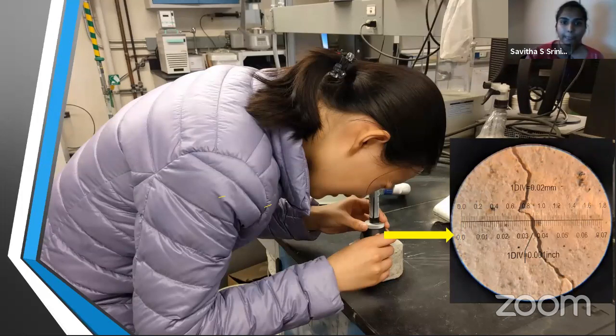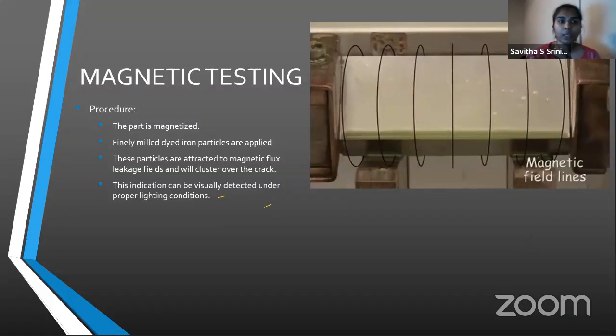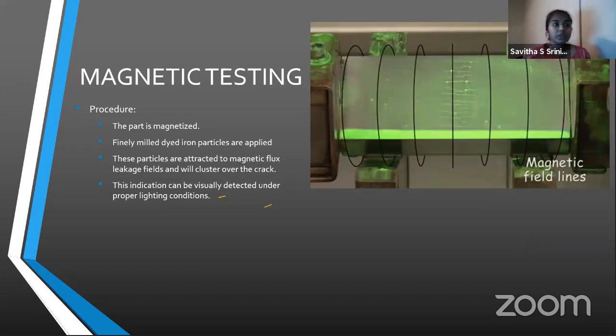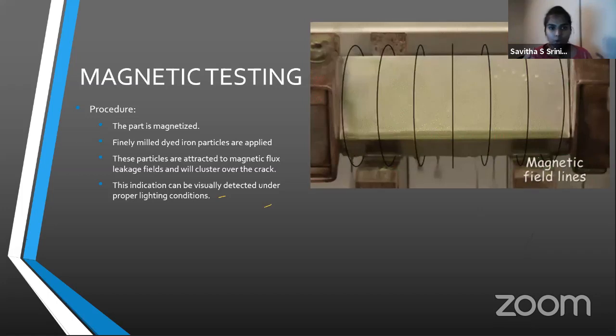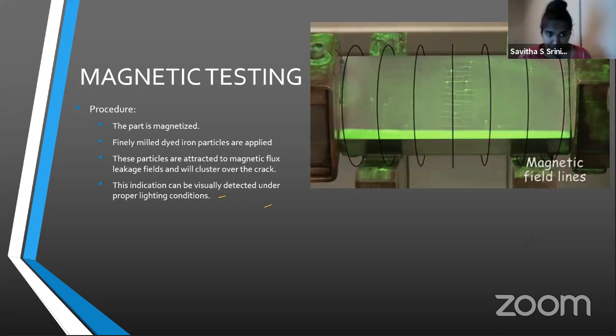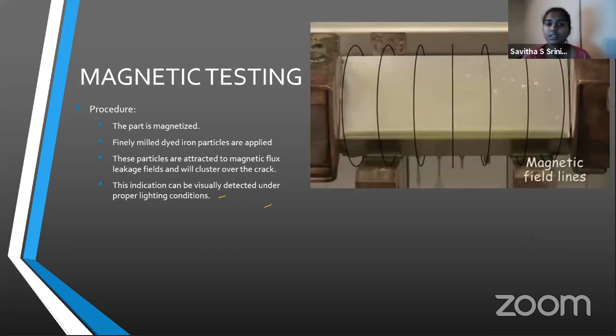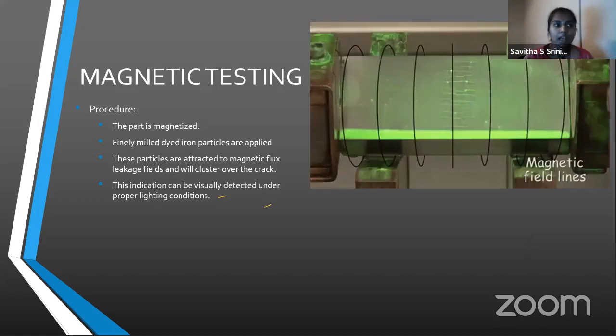The next one we're talking about is magnetic testing. So this one, the procedure is really simple. What you do is you take your part, you magnetize it, and then you add dyed iron particles. These particles are now attracted to the magnetic flux in this material and will sit in cracks and damage spaces. And when you put a special kind of lighting, you can see the cracks that are visualized. This GIF here shows the procedure and how these magnetic field lines are shown.